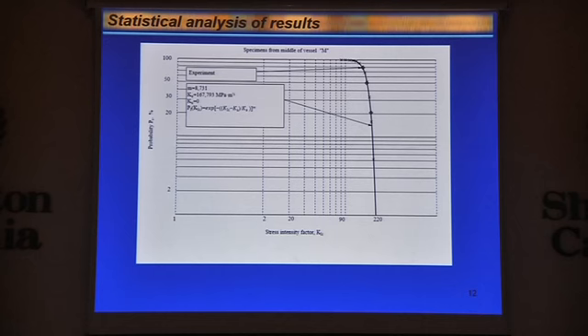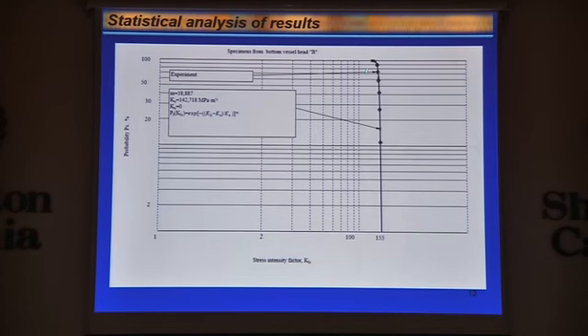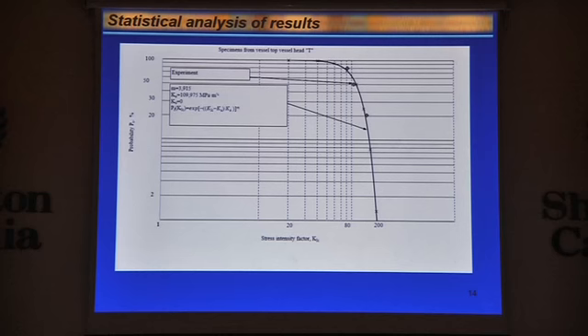We did this for all 3 positions of specimens, and if this line is narrower, of course, then we can say that the results are more reliable, and we can trust these fracture toughness results. In this case, we have some more specimens, and our results are more reliable, so we can use them in fracture toughness assessment procedures, as was used in FITNET, mentioned before, or the SINTAP procedure, or the PD 7910 procedure 2.